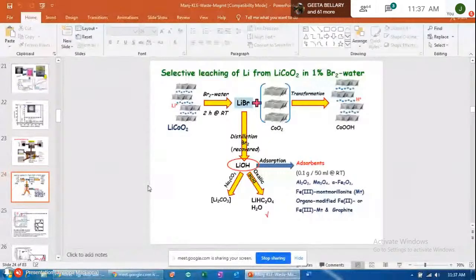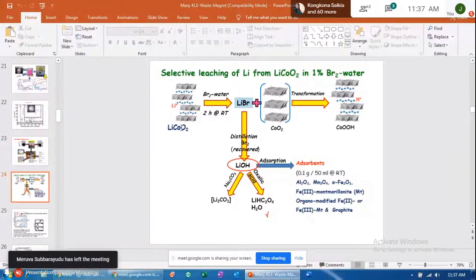What we did, we subjected that lithium cobalt oxide, you are able to see the structure actually. Lithium cobalt oxide itself is a layered structure. The moment I put it in the bromine water, you know that it's a very good oxidizing agent. It oxidizes our cobalt 3+ to cobalt 4+. Once that goes into cobalt 4+, lithium will automatically come out from the lattice. Those who are good in solid state chemistry will be able to understand quickly that lithium has to come out because cobalt 3+ becomes cobalt 4+, that is this cobalt oxide, CoO2. So you see that structure, and lithium bromide is formed.